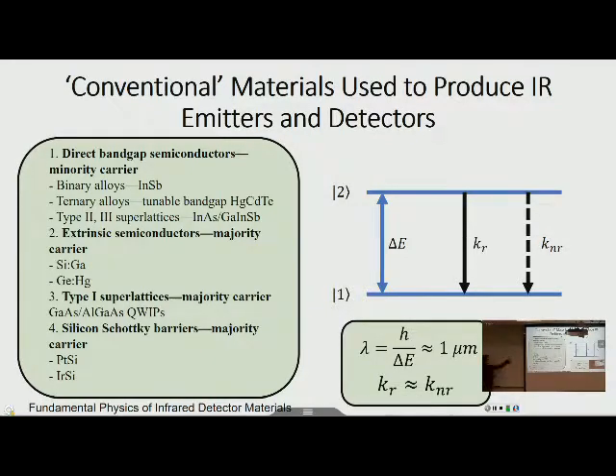Ideally, you would want the radiative rate to be orders of magnitude faster than the non-radiative. Is that physically unrealizable for whatever reason? I mean, is it just not realistic to basically minimize the non-radiative relaxation? It's hard with wider band gaps. You can get quantum yields near 100%, but since you're talking about IR emission, the energy gaps are so small, they're on the scale of thermal fluctuation. That's hard to suppress, thermal excitations and de-excitations within that range. Yeah, I suppose. Because I think mercury cadmium telluride, from the reading, is one of the most efficient. It gets like 50 to 60% quantum yields.